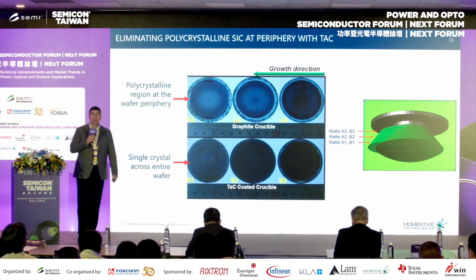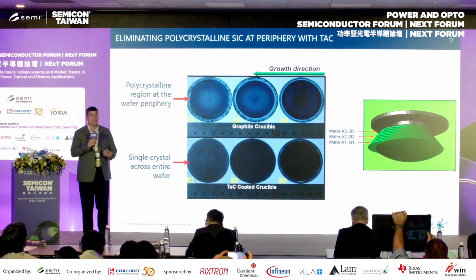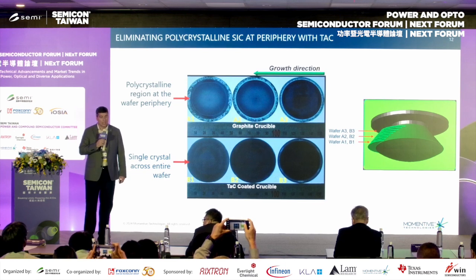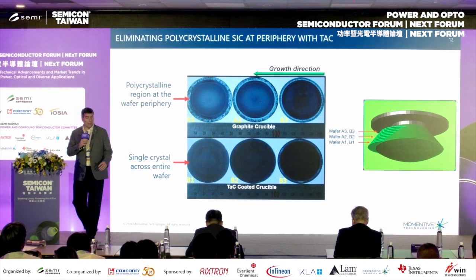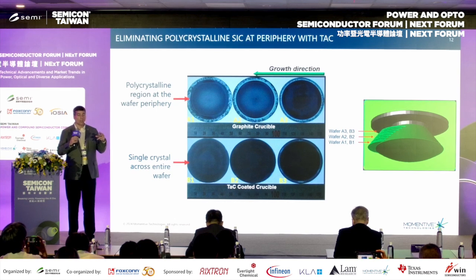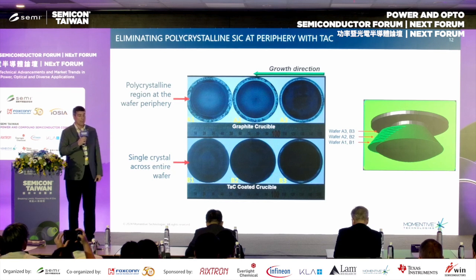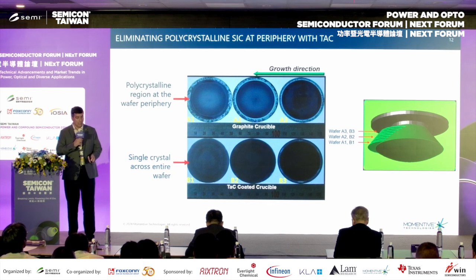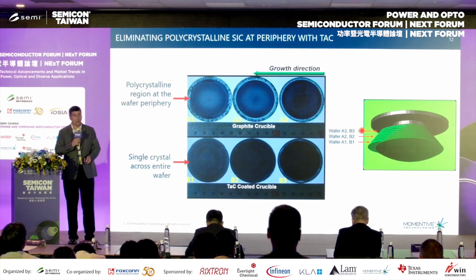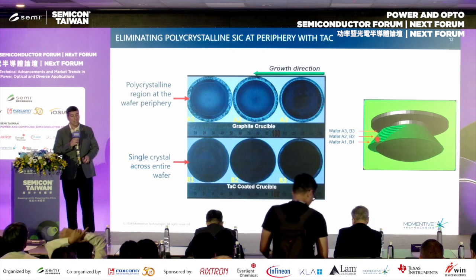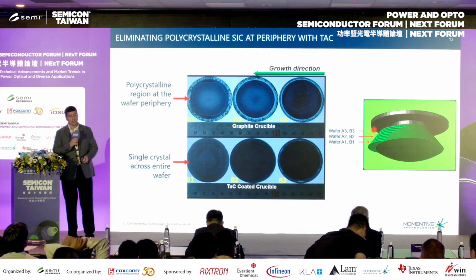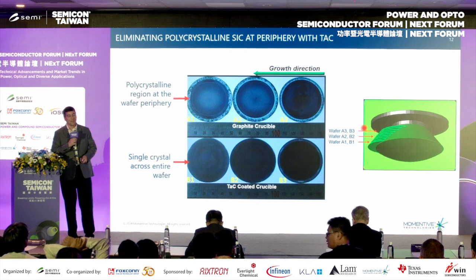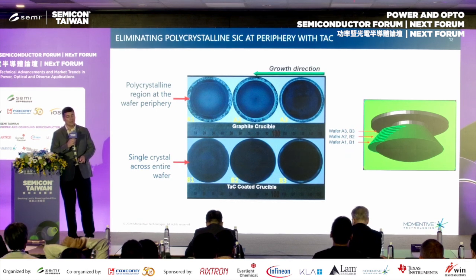When we first started doing some of this work, we did some testing to see how well it impacted the crystal growth. Obviously you're growing the boule of silicon carbide, and you can do that in a standard graphite environment, or you can have the tantalum carbide environment. You can see how the boule is grown, and we're taking the selected pieces, and this is numbered sort of reverse from the way I would have done it. But wafer 3 is grown first and then all the way down. Then they just sliced out.